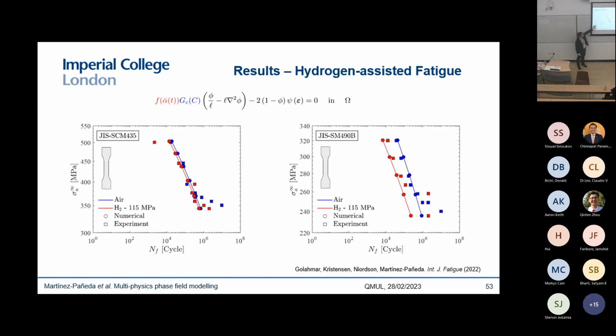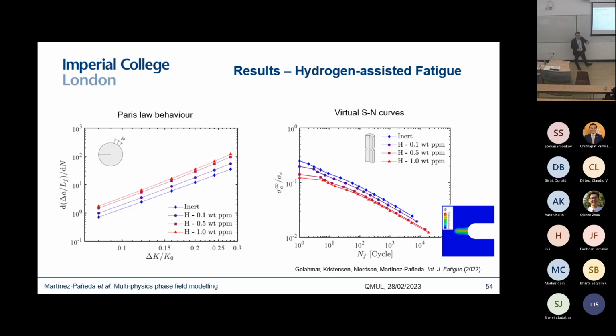And we recently extended this to fatigue, where you have another fatigue degradation function that accumulates with the number of cycles. You can see that we can predict virtual S-N curves, and we get good agreement with experiments. Also, as a natural outcome of the model, we can predict the Paris law behavior as a function of the hydrogen concentration, and virtual S-N curves for any arbitrary loading history or any arbitrary geometry.